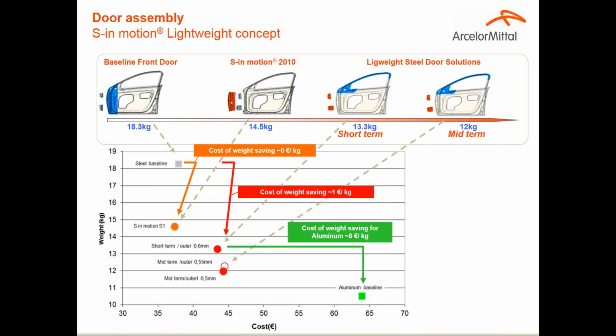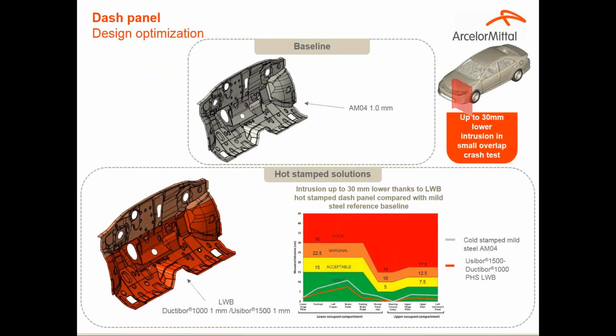Focusing on the small overlap crash test, in fact, by maintaining the same thicknesses and the weight is not changing, we can improve drastically the mechanical, the crash behaviors, just switching from cold to hot stamping, and we can maintain the stiffness where it's needed, thanks to the welding line, and then by combining different grades and materials.